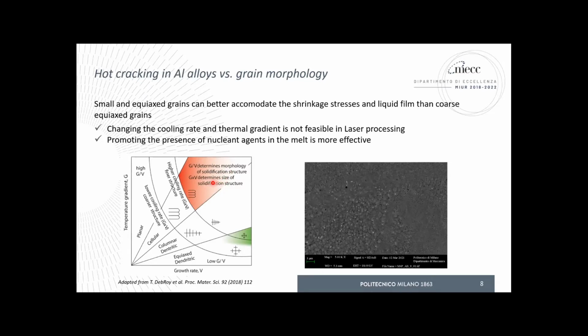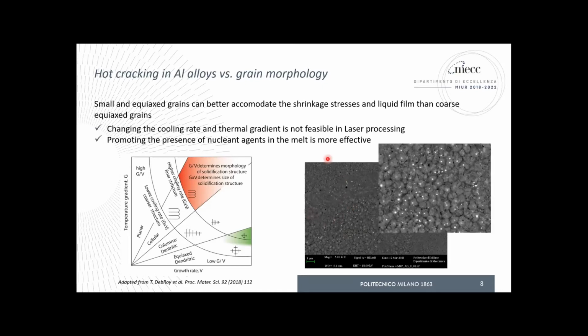The only thing we can do in order to move right here, okay, this could be the region for getting equiaxed grains. The only way for moving toward this region is to act externally by introducing some nucleants, some external particles that could promote heterogeneous nucleation in the liquid. On the right-hand side we have a picture of a structure which was generated by using this strategy, in a 2000 series alloy. I can make an enlargement, in which nucleants were added in order to promote nucleation. I think it's very nice. Maybe qualitatively it's not wonderful, but we can understand very easily that almost all the small grains have a white particle associated to them, which is most probably a scandium-rich particle that stimulated the nucleation of equiaxed grains.